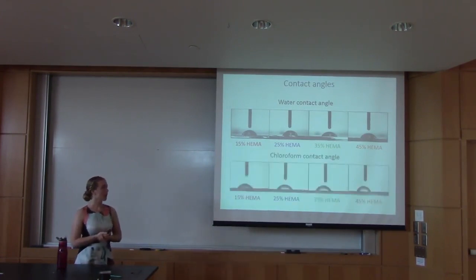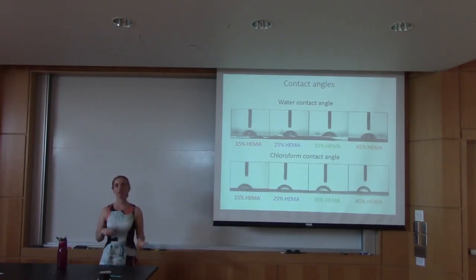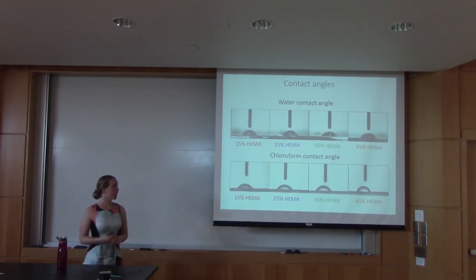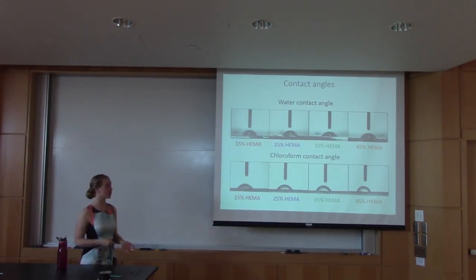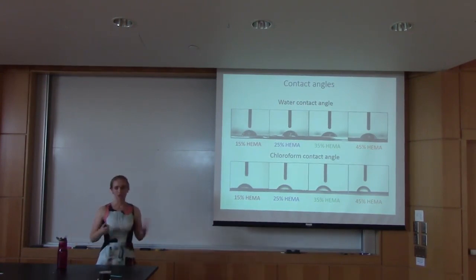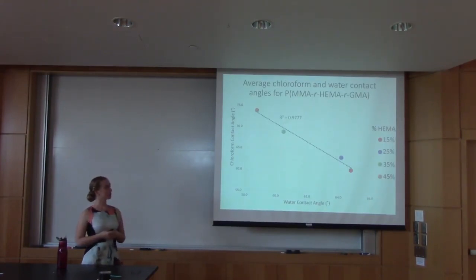On the other hand, we have chloroform contact angle. Now chloroform is essentially the opposite of water. It is highly hydrophobic, and so we can see the opposite pattern here. As we increase in the amount of HEMA, our droplets become much more curved, and there's a lot higher surface tension and higher contact angles. So we have this general trend, and now what we do with that is we have this graph.